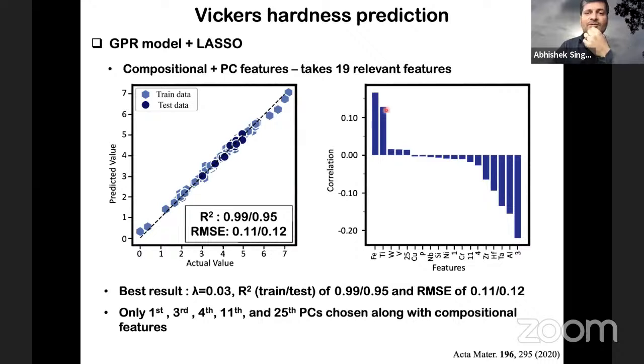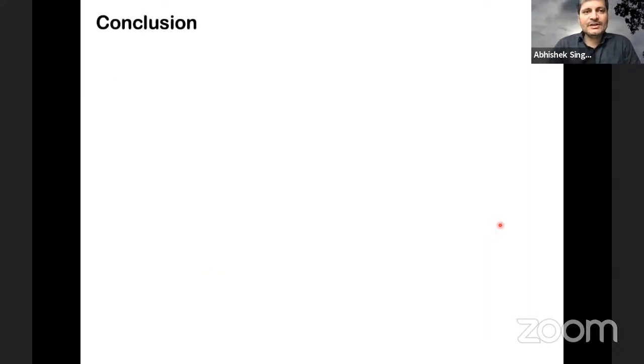We find some of the correlations which were known in the metallurgy community. For example, iron has a positive correlation with the hardness if you add iron, and aluminum has a negative correlation with the hardness, and this fact is known to metallurgists. As I told you, we do not always expect causality, but many times in machine learning, we can learn from the machine also, which was true in this case too.